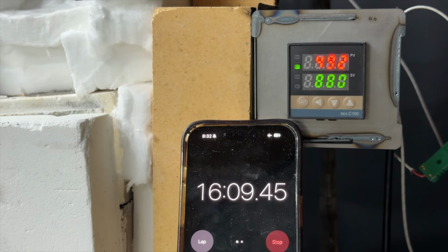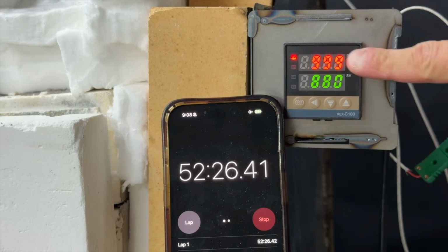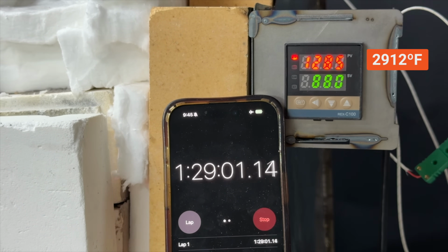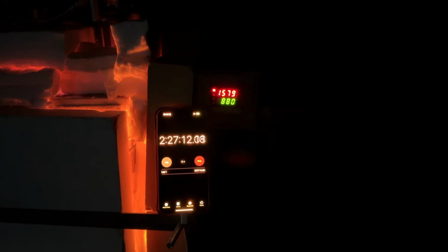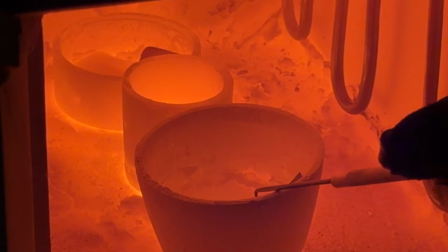So we power up the furnace and it took about 2.5 hours to reach 1600 Celsius. Here's our DIY box furnace glowing at almost 2900 degrees Fahrenheit. That's almost 1600 degrees Celsius. This is way hotter than most DIY box furnaces that you're gonna find on YouTube. So the furnace tapered off at 1600 C, which forced us to stop.